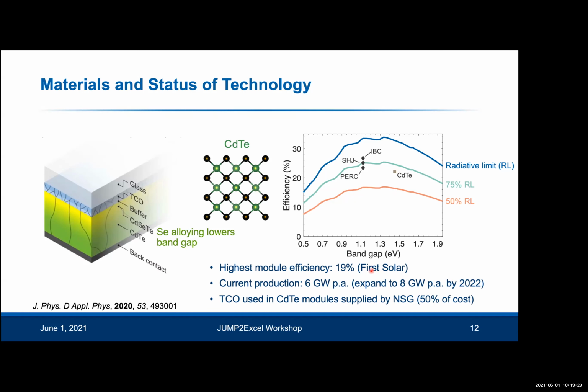So right now, the scale of production of cadmium telluride isn't as high as for silicon. In fact, it's more than an order of magnitude lower than that for silicon. But still, compared to other emerging technologies, the scale of production is relatively high. It's 6 gigawatts per annum, and that's expected to expand to 8 gigawatts per annum, which may have already been reached. And the UK has a very strong stake in this technology.